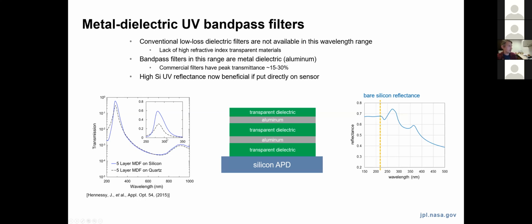So here on the left, I'm showing some examples of some of these metal dielectric filters that were optimized for a wavelength around 275 nanometers, showing the effective transmission that you get for a stack on a transparent substrate like quartz, so relatively modest, 30% peak efficiency. And then the transmission that you get if you integrate the same stack onto silicon. And you can see you get more than a 2x improvement in the end-to-end transmission of these multi-layer filters.